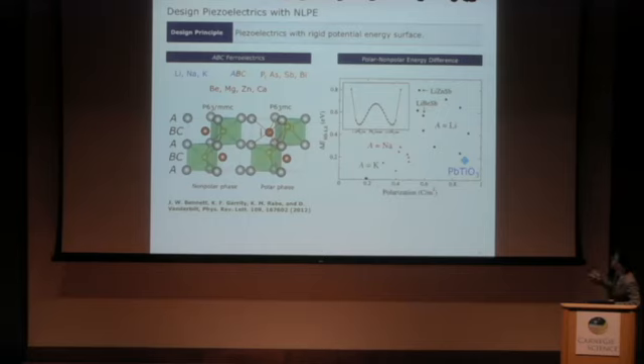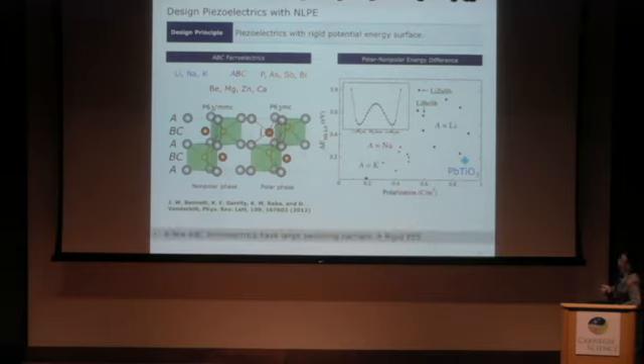So as you can see, a lot of ABC ferroelectrics are quite rigid. They have very large switching barriers. Particularly for those compounds containing lithium atoms, and lead titanate, I think roughly the barrier height is around 0.2 electron volt per formula unit. So clearly, these ABC ferroelectrics are much more rigid than lead titanate. So I think they are very good candidates to start with.